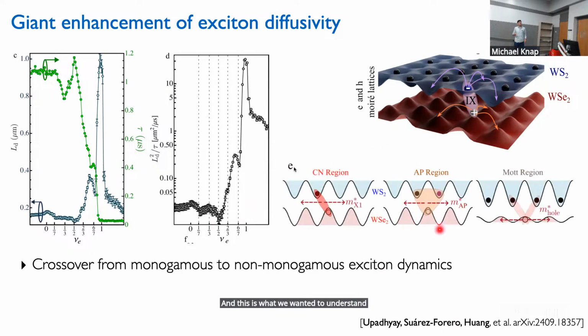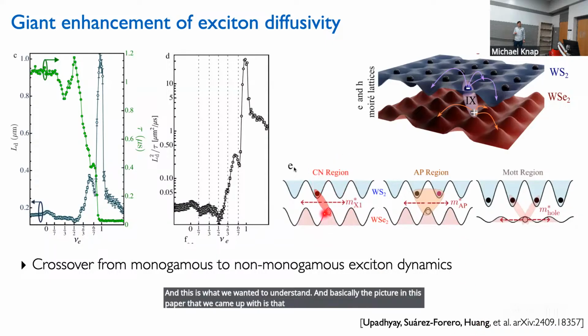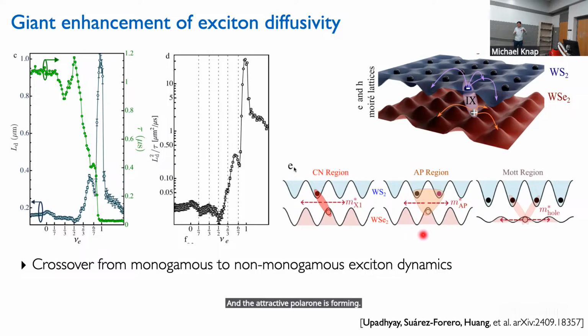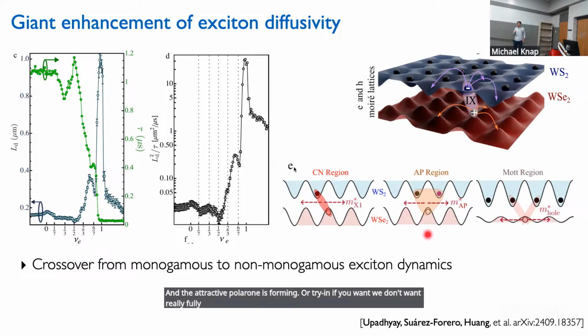And basically the picture in this paper, what we came up with is that, if you have a charge neutral region, the exciton is hopping around. When we start doping, then actually an attractive polaron is forming, or a trion, if you want. We don't really fully know, but surely it has a different effective mass. So this means that the transport properties should change. In particular, it gets heavier. This leads to a reduction of the diffusivity, as seen here in the experiment.